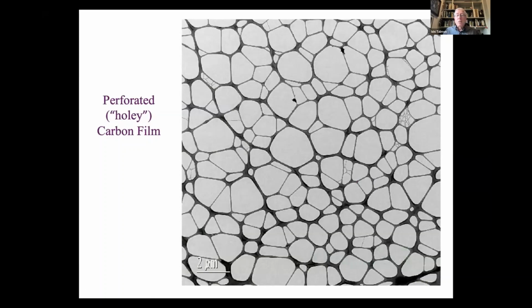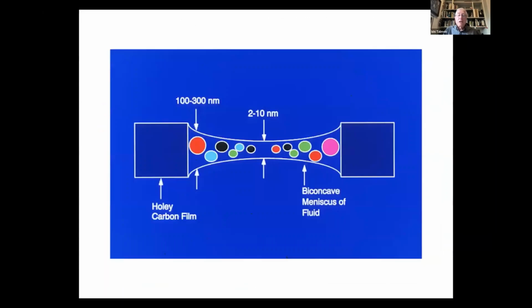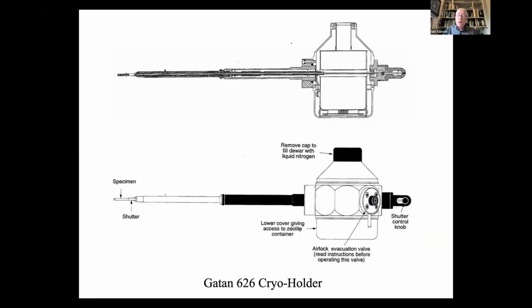So this is just a perforated carbon film, the dry one. In principle, each one of these holes we want to support a thin liquid film. Here is the schematic of one of these holes, and you see the liquid film that spans the rim of this hole. And here you can see some of the typical thicknesses that we have: in the thinnest areas, 2 to 10 nanometers, and in the thickest area, not more than 300 nanometers. This, of course, is a limitation of how big an aggregate we can fit in this film.